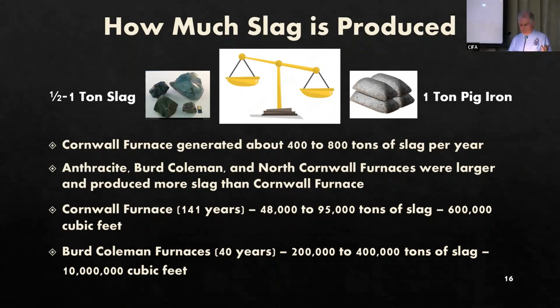In contrast, Burd Coleman furnaces, and there were 2 of them, produced about 10,500 tons of cast iron a year. If we use those amounts as representative for the furnace production of iron, that means that the Cornwall furnace would have generated between 48,000 and 95,000 tons of slag during its 141 years of operation. In contrast, Burd Coleman furnaces would have generated between 200 and 400,000 tons of slag during their much shorter lifetimes. If you convert those tons of slag into a volume, and you account for the differences in the furnace and the compositions of the slag, Cornwall furnace produced about 600,000 cubic feet of slag, and the Burd Coleman furnaces produced about 10 million cubic feet. That's a lot of slag.